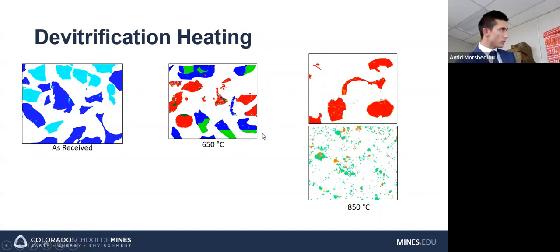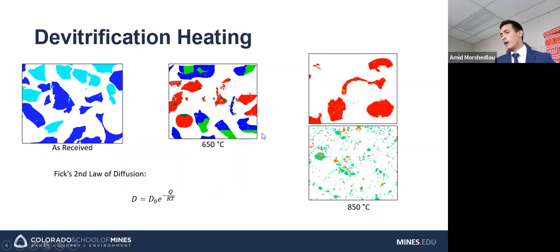So we have different amorphous phases here, but we're still pretty amorphous, not crystalline enough to be useful for our purposes. So we go up to a higher temperature, and we can see that the fine stuff has crystallized pretty well, not completely, but we're happy with it. The coarser stuff still has that different amorphous phase that we can see in the 650 samples. So this tells us a few things. One, we are getting some devitrification, some crystallinity in this sample, which is good. That's what we want. But 850 for 2 hours and then furnace cooled tells us that devitrification is pretty slow. And we can look at Fick's second law to help us with this.